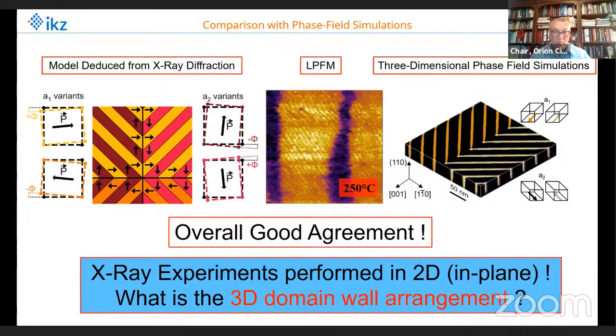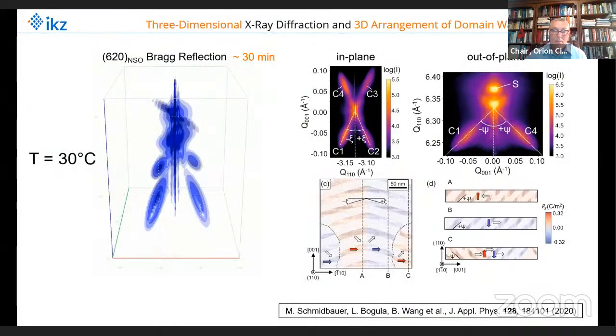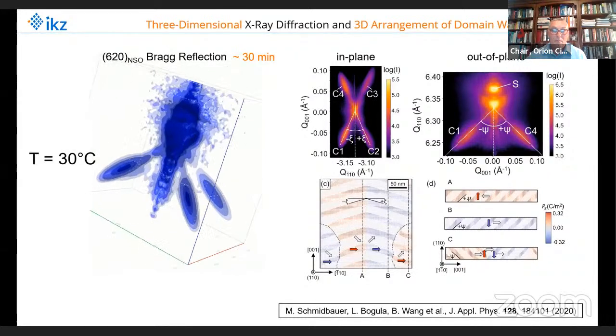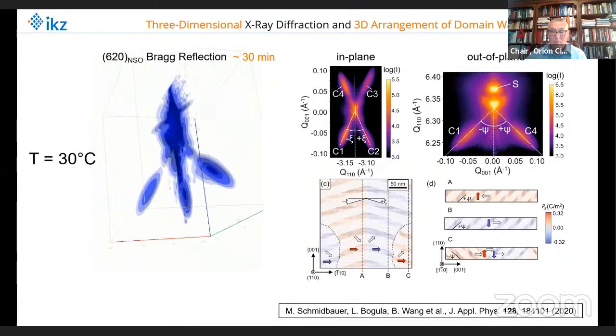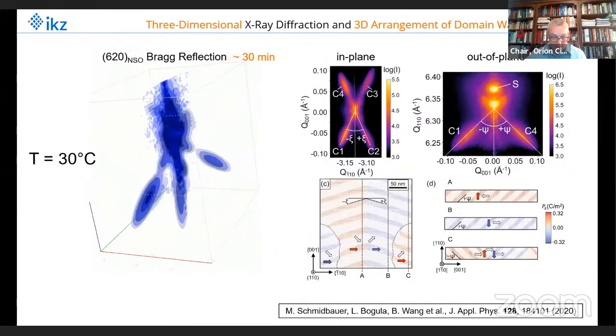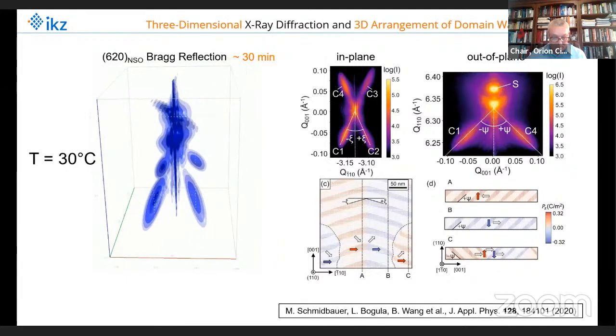So far I have shown you only experiments performed in 2D, so in plane. But what is now the 3D domain wall arrangement? For that reason, we have performed true 3-dimensional X-ray diffraction in order to determine the 3D arrangement. You see here on the left side a 3D diffraction pattern, which took only 30 minutes. And we see here 4 prominent streaks coming from the domain walls. So we have 4 different domain walls.